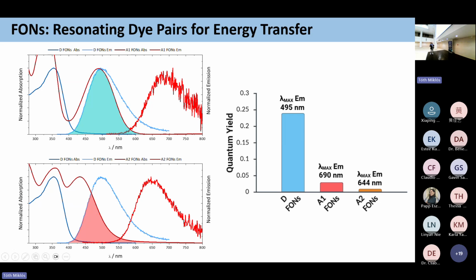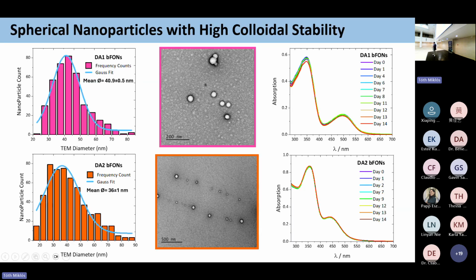So we determined the quantum yield for the single component particles, obtaining the interesting value of 24% for the donor and the lower values of 3 and 1% for A1 and A2 respectively. We prepared the binary nanoparticles starting from a mixed stock solution of the dyes in which the donor is present in excess with respect to the acceptor, and from transmission electron microscopy, we saw that we have produced spherical nanoparticles with a quite homogeneous size distribution, with a mean diameter of about 40 and 36 nanometers for the A1 and the A2 respectively. And by collecting the absorption spectra in the same conditions over a period of 2 weeks, we have seen that there is also a quite remarkable colloidal stability.